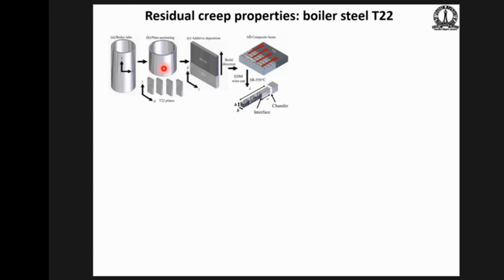So what we did was we cut these coupons out from the tubes. Some we tested as monolithic coupons, and others we additively put a handle of an inconel. So in a sense, okay, this is my cantilever. The portion which is deforming is the steel, which is over here. But the strain over here is more or less irrelevant because the stress drops off so fast that the strain rate becomes negligible. So this can be replaced by an inconel. You just want something which is stiff and doesn't deform. Otherwise, this portion will bend into U and nothing will happen here.